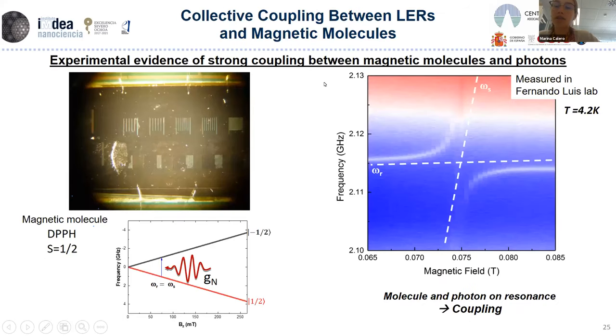When we have the bare resonator characterized, we try to couple some magnetic spin ensemble to one of the pixels. Here, for example, we try to couple a free radical called DPPH with spin 1/2. This represents the energy level diagram of our magnetic molecule, and we can see how, by changing the external magnetic field, we can change the energy levels of the molecules because of the Zeeman effect.